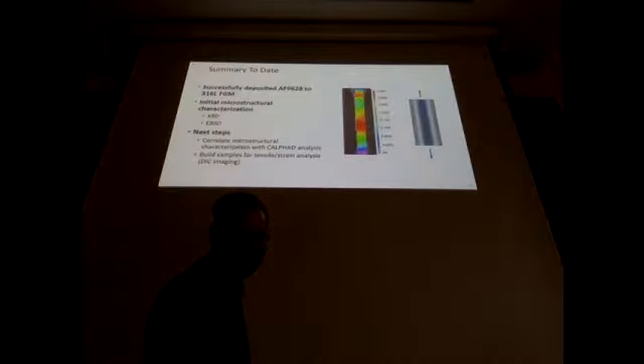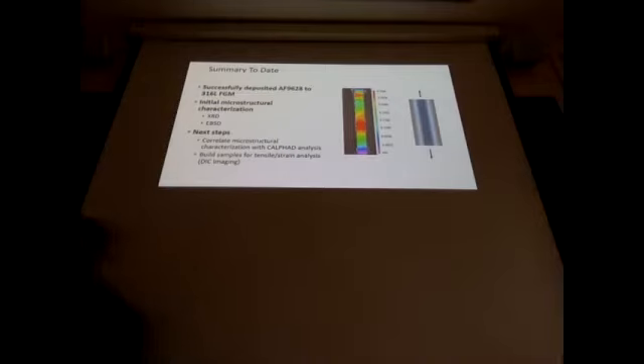And then this is just the inverse pole figure color map, that EBSD data, to show the fine structure that we're seeing. It actually looks fairly fine in grains, and then we move over to almost a columnar grain as we move up to the stainless steel. And it actually does look very columnar as we get into that stainless steel. So that's kind of our summary today.